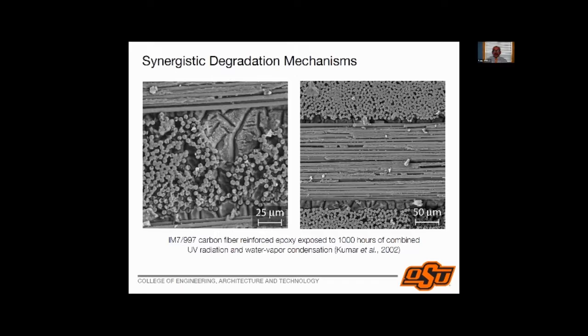And when you get this physical removal of the epoxy, you start degrading the fiber matrix interface. And if you start degrading the fiber matrix interface, now you don't have a mechanism for transferring the loads from the matrix to the fibers. So if you're familiar with composites, the way composites work is that you have these carbon fibers inside the matrix. And when you load it, there is load transfer that occurs from the matrix to the fibers. And the fibers take the load, but the matrix has to provide this load transfer. And this load transfer goes through this fiber matrix connection. So that connection is very important, and how that connection changes if you expose it to different environments becomes very important.